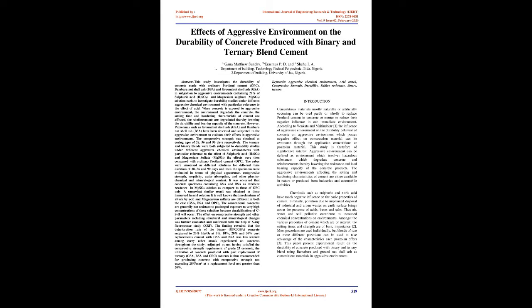However, pozzolans such as groundnut shell ash (GSA) and Bambara nut shell ash (BSA) have been observed and subjected to the aggressive environment to evaluate their effects. The compressive strength was obtained at curing ages of 28, 56, and 90 days respectively.